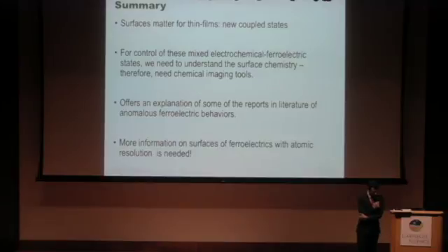So as far as I know, its strain is quite small on dysprosium scandate. 1%. Right. It's okay. Well, whenever we do the lateral PFM studies, we're unable to find any signal that would suggest an in-plane polarization, is all I can say. Yes. So could you measure as well in-plane polarization? Well, we can measure the in-plane strain, yes. If it exists, we can do it, yes. Okay. Yes. Thank you.